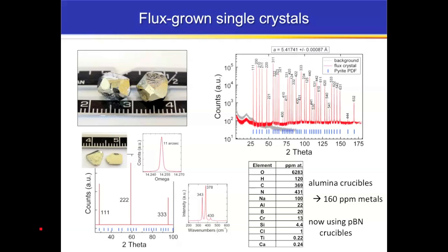We can characterize by Raman spectroscopy. We can characterize it by synchrotron XRD to show that it is in fact phase pure. And we do full periodic table elemental analysis to find out really what's in these crystals. And we find that we've got about 160 part per million metals impurities in these crystals. So these are the biggest pyrite crystals and the purest pyrite crystals that have been made to date.